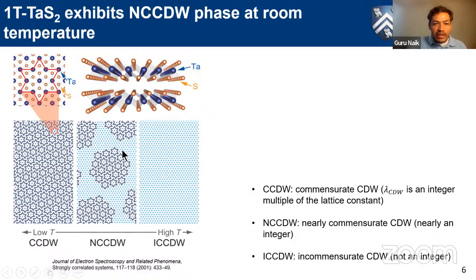So it also shows peculiar phase formation, which is that there are domains where the material has condensed into these charge density waves. The charge density waves, in fact, show up in this material as this David star formation, where 13 tantalum atoms slightly dislocate from their lattice centers, just a fraction of a picometer, to host exactly one charge in them. And these David stars interact with each other, making a charge density wave domain. At room temperature, this material has many of these domains, and in between these domains, we see that there are metallic regions where conduction can happen. So this is a metal at room temperature.